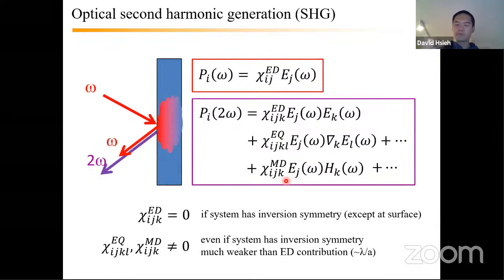So for example, this electric quadrupole response, which is a rank 4 polar tensor, is allowed even in the bulk of inversion symmetric materials. That becomes a dominant response in centrosymmetric systems. As does a response like the magnetic dipole, where you're now dealing with an axial third rank tensor, which is allowed even in the presence of inversion symmetry. So the crystals I'll talk about today are largely, crystallographically, inversion symmetric. And so we'll have to contend with this competition between potentially surface, bulk electric quadrupole, bulk magnetic dipole terms, and so on.